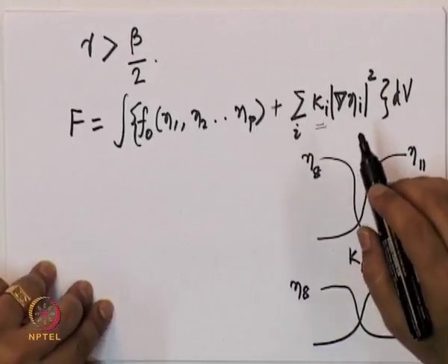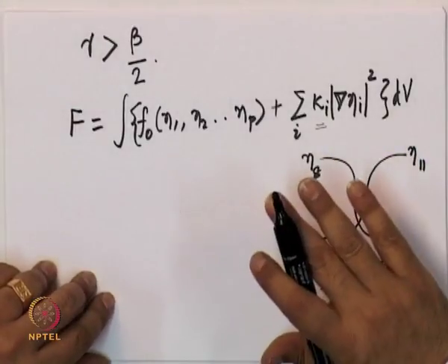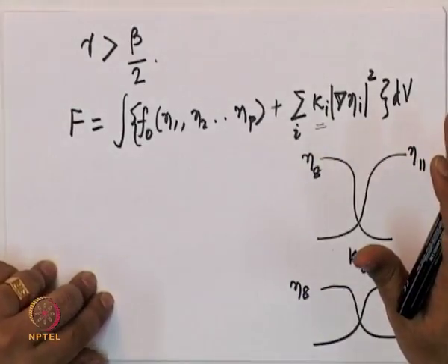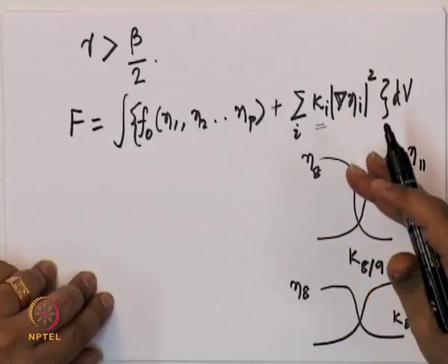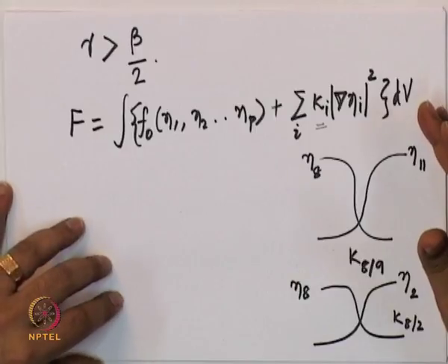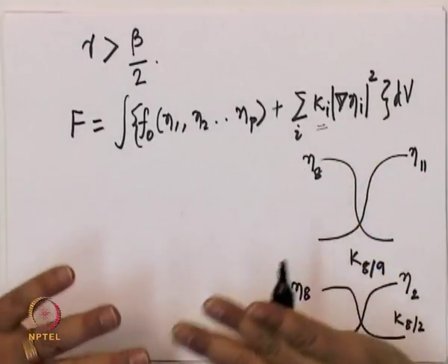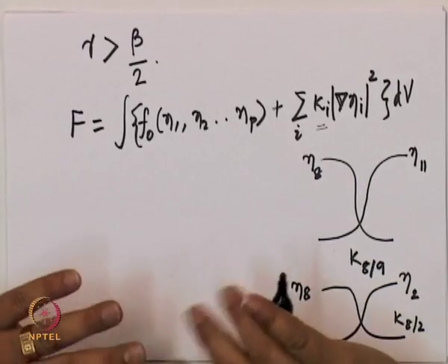Okay. One of them for classification, for example, describes grain boundaries as small angle grain boundaries and high angle grain boundaries. Okay. But actually a grain boundary has 5 macroscopic degrees of freedom, and there could be special orientations in which the grain boundary region will have perfect matching across planes. So it will have very low energy. Those are known as CSL, or coincident site lattices at the boundary, and so on and so forth.